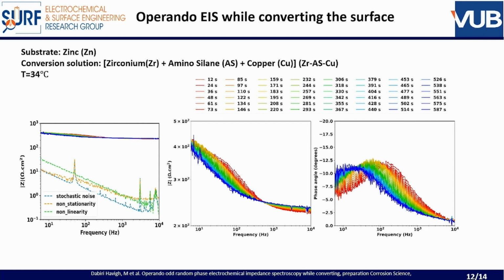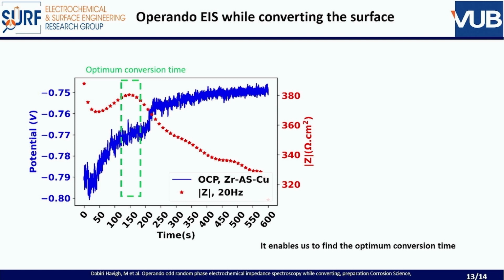It also allows you to fit the impedance measurements and recalculate them, and then you see when you reach the noise levels. At that moment we don't add any more components, for the simple reason that you would start to model the noise. So this is, for example, the low frequency amplitude followed as a function of the OCP value, and out of that we can even optimize the best conversion time for a particular system. Especially for these conversion systems where they add fluorides and other redox systems like copper, it is interesting to see the individual contribution of all these components in the formation of the layer.